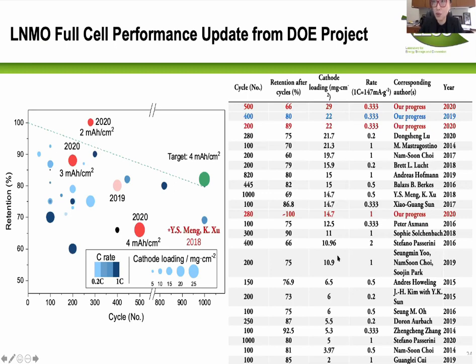Again, a literature review is so important, because for all these great retention cycling numbers, the loading is so low it's really irrelevant for the battery industry, right? And where we want to be, and where we can achieve... we did achieve something with a very small cell, very low loading, but that's not counted, right? Because the target is you need to scale, 4 milliamp hour per centimeter square, and that's still quite a big challenge. The reason for that is because many of the new cathode materials require high voltage operation.